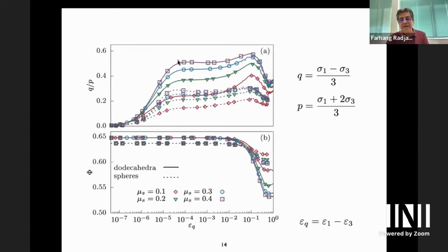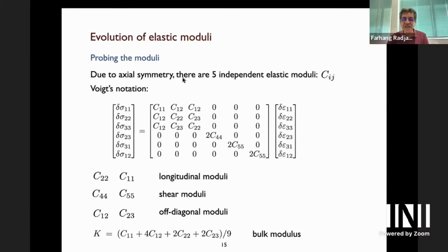to evaluate the elastic moduli, because here the strains are too large, and basically we are looking at the change of state. We are not, with elasticity, looking at the change of state, but at the state at a given time. So the strain probe, or strain that is applied, should be low enough in order to avoid the deformation or the rearrangements of the packing.